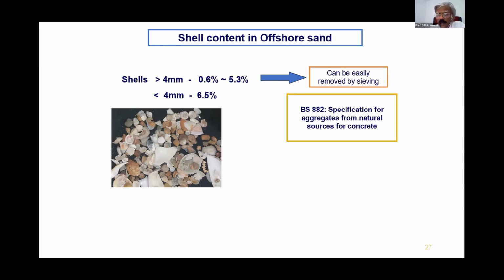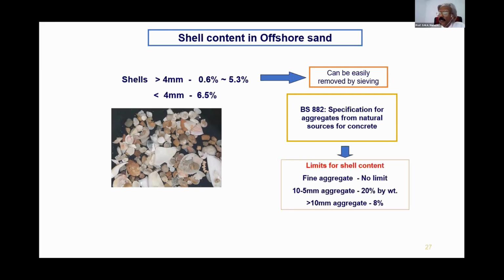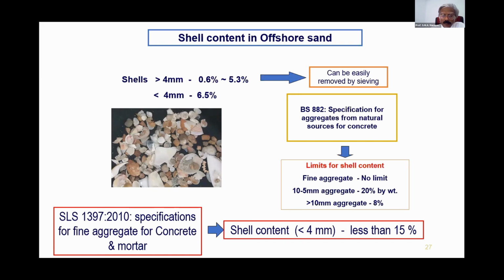Now, there's a standard, BS 882, that gives the specification for aggregate from natural sources for concrete. There you can find limits for shell content. Interestingly, there's no limit specified for fine aggregate, but you can find the limits for coarse aggregate, that is larger particles from 5 to 10 millimeters and more than 10 millimeters. Now, if you refer to the SLS standard, the Sri Lanka standard specification for fine aggregate for concrete and mortar, there the shell content is limited to 15%.